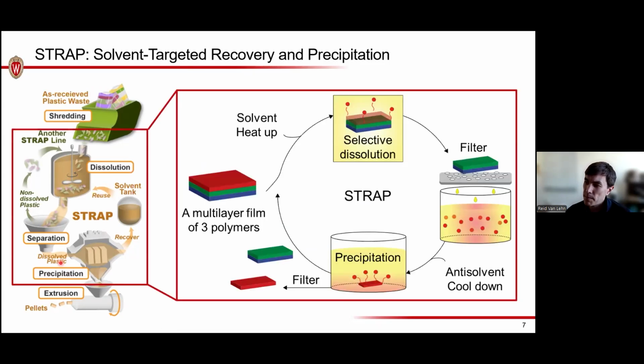Okay, so let me explain what that means. If I look at this cycle that I'm showing here, imagine I take a multi-layer film that has, for the sake of example, 3 different polymer components, okay, red, green, and blue. Of course, many materials will have more than that. The idea of STRAP is to say, what if we choose a solvent that can selectively dissolve one of those polymer components, but not the others? So we're relying upon the thermodynamics of mixtures. We're relying upon the idea that certain solvents will have a chemical affinity for certain polymers that allow us to dissolve that polymer, but nothing else.